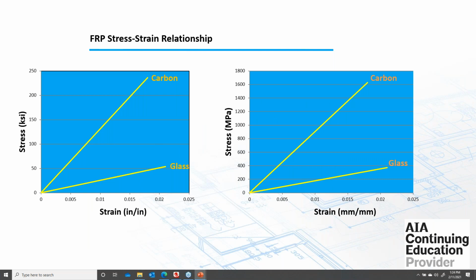Just don't want to spend a lot of time here. Just the one thing to point out, this is obviously a stress strain diagram. The important takeaway from this is that these materials are linear elastic right up until failure. So it's not like steel where you've got your yield point and it kind of tops out and then starts yielding and then starts reducing a little bit until you get to your failure point. With FRP materials, they're just going to keep taking load, and then all of a sudden you're going to get a sudden failure as far as tensile strength. Now, we never are able to achieve the ultimate tensile strength of the material, and I'll explain why that is in a few slides. That's why the ultimate tensile strength is really not all that important, because we'll never get there. It's going to delaminate before that happens. So just to point out the difference between steel and FRP is that it is linear elastic all the way up until its failure point.